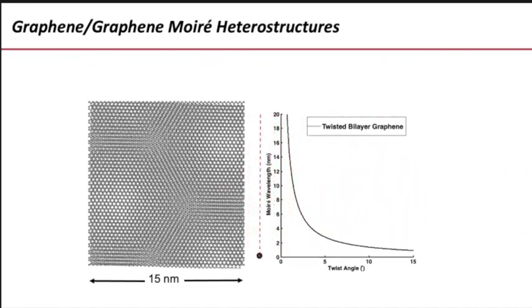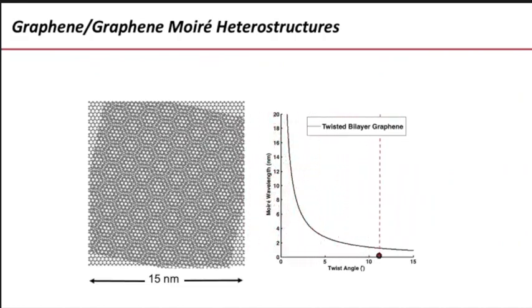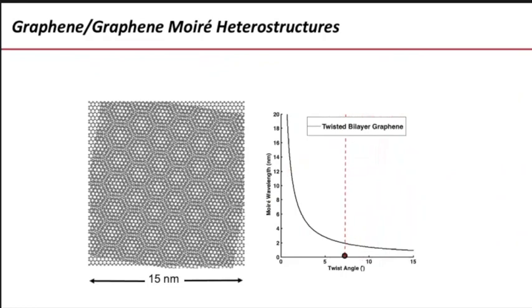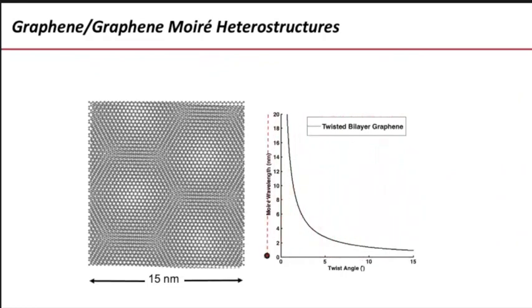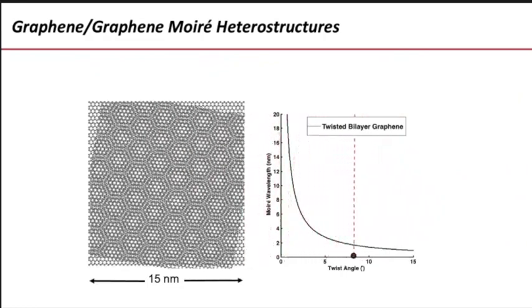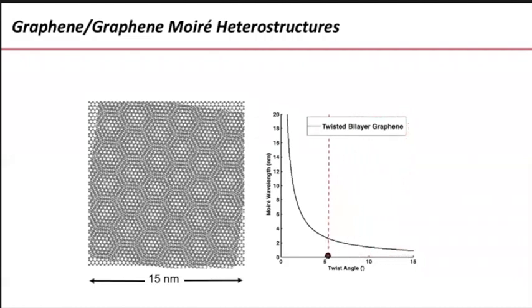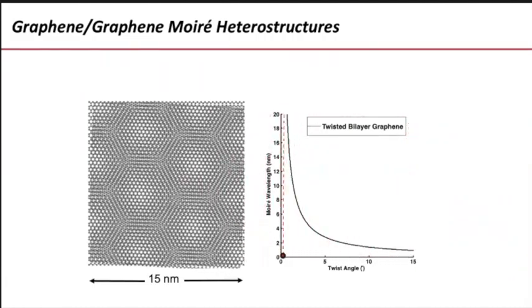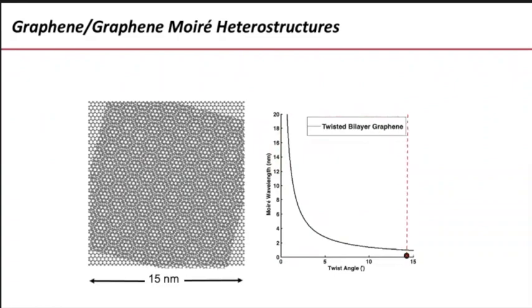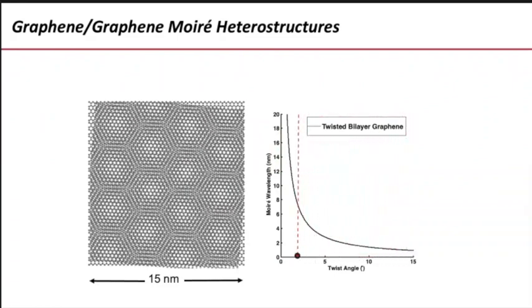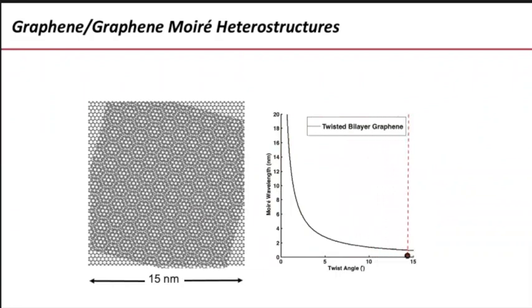But in general, a Moiré pattern forms where the Moiré wavelength, the distance between the soccer balls that you see here on the screen, goes as one over the twist angle, particularly at low angles, okay? Because these lattices are identical, these Moiré wavelengths can go all the way to infinity. If the lattices were slightly different, then it would saturate at a maximum Moiré wavelength. Now, this is what happens in real space.